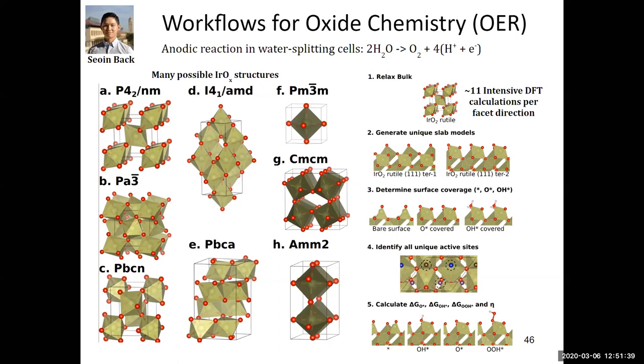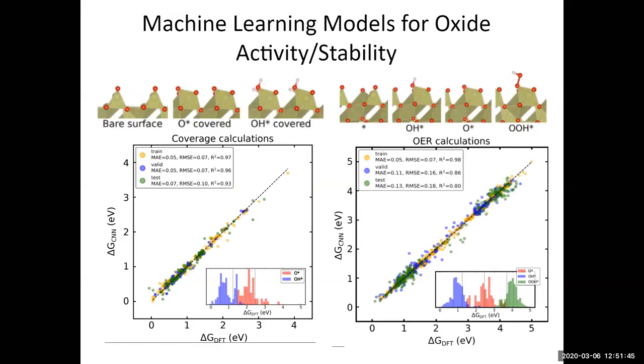This is work that Seoin, the first postdoc in my group, was doing. We built a workflow for iridium oxide polymorphs. We showed that similar graph convolution methods can help us predict what is the stable termination and what is the best site or the energy of oxygen or OOH at different places.